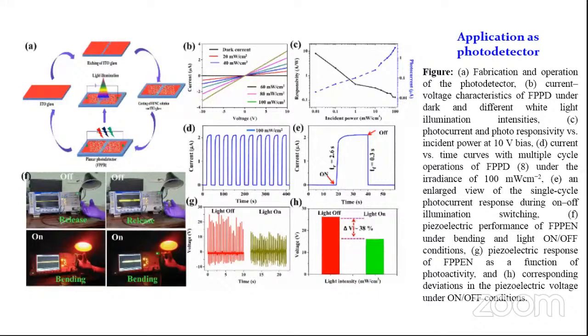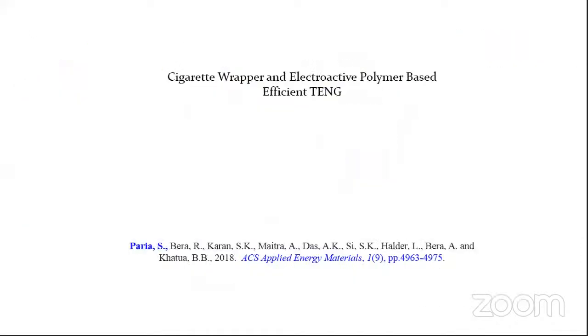So what is the connection between our fabricated energy device and light? We have seen that formamidinium lead bromide is a semiconductor. When we are irradiating, there will be some exciton generation. That exciton will reduce the piezo potential of the PVDF. So when we are measuring, we get less voltage on application of light. That reduction is actually 38.8%, which clearly reveals that it can easily detect the light through the piezoelectric effect. So it can be useful as a photo detector.